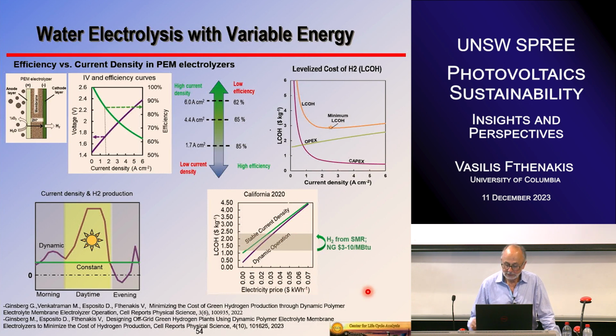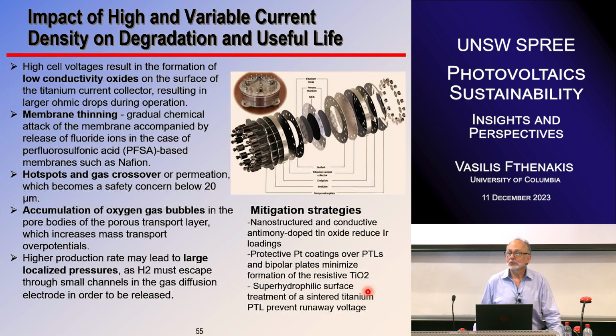Now, this doesn't come as a free lunch, because when you have higher current densities, you can have more damage, more degradation. We model certain assumptions in terms of degradation. You can see here some highlights of the typical degradation mechanisms at higher current density. You can have low conductive oxides, membrane thinning, hot spots, oxygen gas bubbles, large localized pressures, and gas diffusion, where you can lose both hydrogen and oxygen and create some risky conditions.